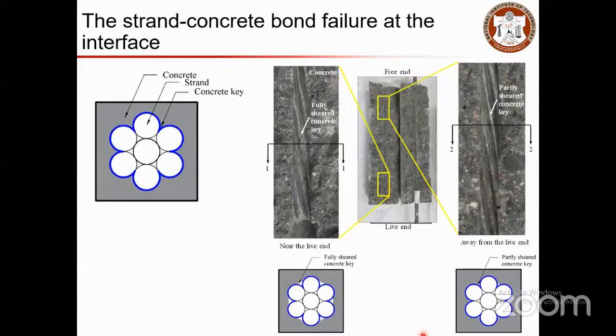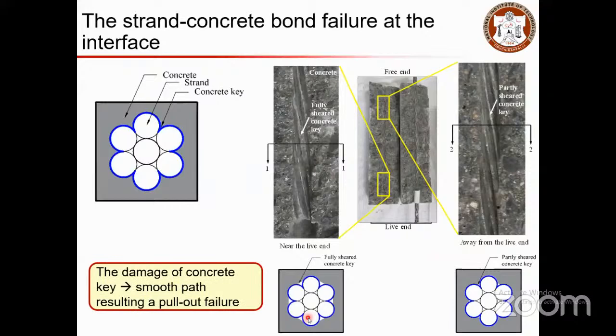For helical shaped strands embedded in concrete, the bond failure is different. You have a shear key formed, and as the strands are being pulled out, these shear keys also get deformed, and partially the shear keys get cracked at the initial stage. Here you can see the shear keys are completely cracked, and this is going to give you a pipe formation through which the strands are going to pass smoothly. The damage of the concrete key, a smooth path, results in pull out failure.